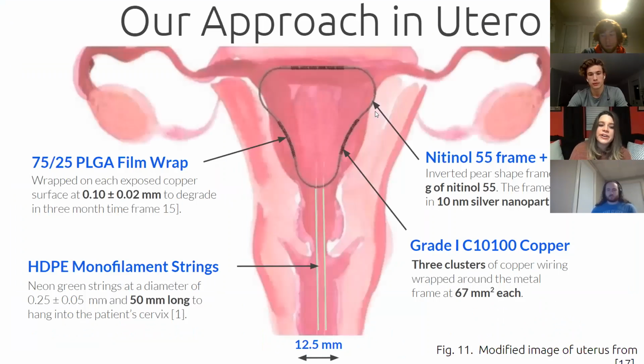In considering uterine anatomy and the unmet clinical needs that the aforementioned copper IUDs do not fully address, we propose a galvanically corroding copper-based intrauterine device. Our device frame presents as an inverted hollow pear shape, measuring 32 millimeters long and 3 millimeters thick. The transverse width tapers from 25 millimeters to 12.5 millimeters, with 2 50-millimeter strings for device check and removal. Our device will manipulate 5 raw materials to create an improved patient experience and better clinical outcomes.